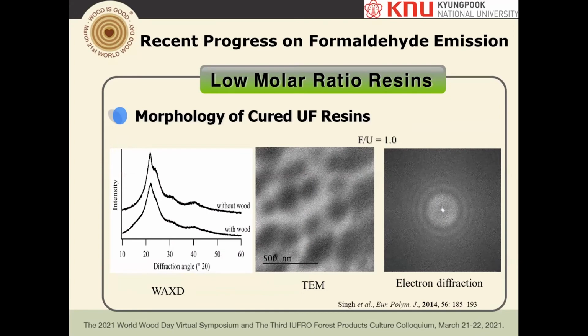And then we look at these resins with XRD, with wood, without wood. They're pretty much the same crystal patterns, and with wood, a little bit smaller size. And then we also did the electron diffraction, which gives a different number of rings, which means these crystals are polycrystals. I mean, different types of crystals are combined together at the same place.